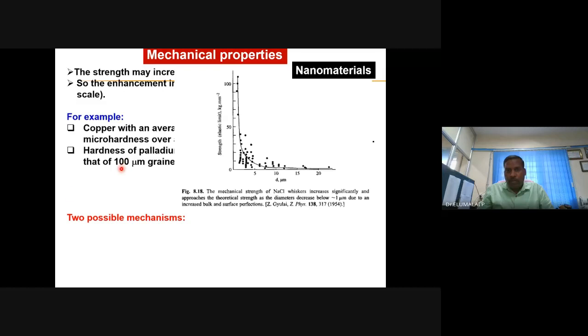You see here, this is for sodium chloride. Somebody made sodium chloride whiskers. What are whiskers? Spikes, like needle-like particles, and they measured their elastic limit, the strength they have. So they had sizes of 20 micrometer, 15 micrometer, 10 micrometer, 5 micrometer, 2 micrometer, 1 micrometer. What do we see? As the grain size decreases, strength increases. And they are not nano, still micron.